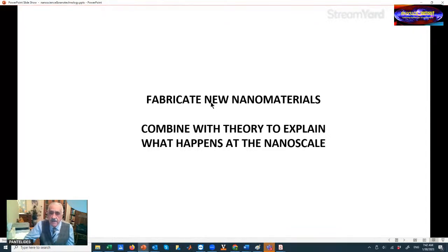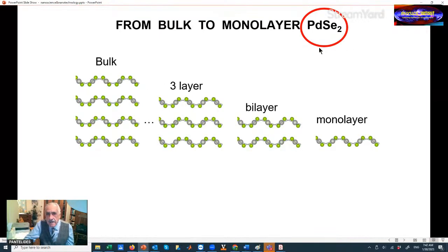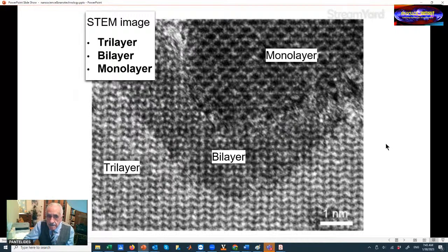So I'm going to show you now how you can fabricate new nanomaterials, not just nanowires. And then we can do physics by combining theory with microscopy to explain what happens at the nanoscale. Here is a layered material, palladium diselenide, and it's layered like this. This is the individual planes, the individual layers that have 3 planes of atoms. This is theoretical analysis now that says in principle, you could thin it to 3 layers, to bilayers and monolayers. And a number of people studied the properties of the monolayer. But again, my former student, Jun Hao Lin, thinned the material with the electron beam in the microscope to bilayers and monolayers. But the big surprise was the structure of the monolayer was not what was expected.